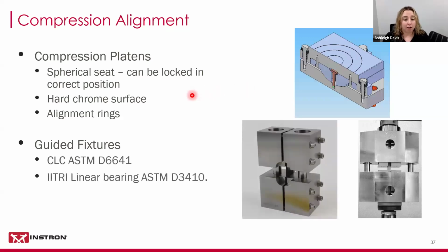And then there's a variety of composites compression fixtures, and these integrate guidance and alignment in the fixture themselves. Shown here on the left, we have the combined loading compression fixture, or CLC, and the IITRI compression fixture on the right. Both of these are supplied by Wyoming Test Fixtures. And these fixtures are designed and manufactured to be laterally stiff, well-guided, with very low machine tolerances, and then they do sit between that pair of compression platens. The guidance and the alignment comes from the fixture itself rather than the machine.